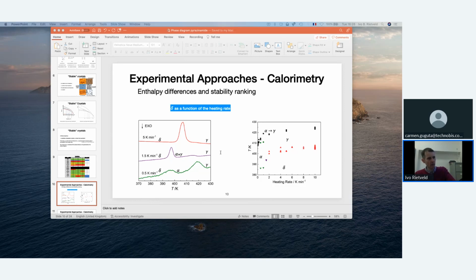And by cross-referencing this to a series of experiments, we could put the finger on the equilibrium temperature of 392 Kelvin or 119 degrees Celsius. But that was quite a bit of work. Now, this DSC measurement, therefore, gave us the possibility to have, on the one hand, enthalpy differences, and the oven gave us at least an idea about the equilibrium temperature between alpha and gamma. But the rest was much more difficult.